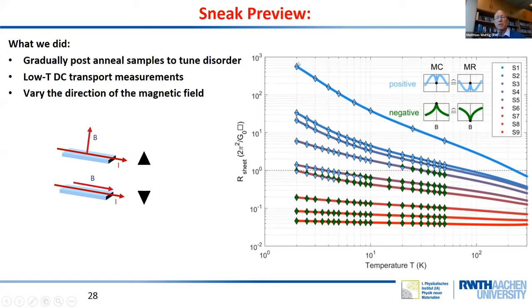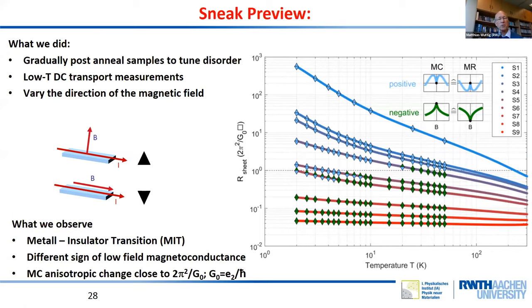And we start with a very insulating sample, which is crystalline. And step by step, we make it more metallic. So we go from blue, insulating, high resistance at low temperature, to metallic, showing low resistances at low temperatures. So there's a clear transition from an insulating to a metallic state. Now this is the blue and the red curve of these lines. So the first point: clearly, what we observe is a metal-insulator transition.